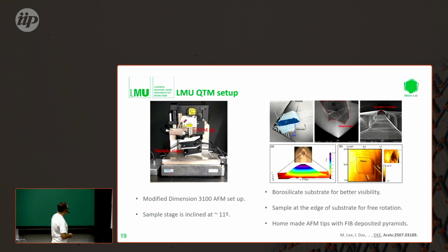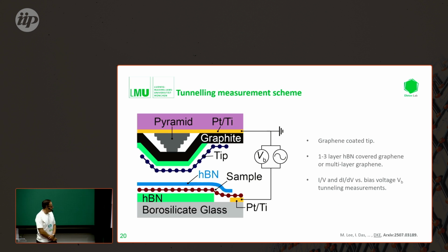Okay, so for the twisting microscope, we followed Shahal's lead, so we first built a room temperature setup of it, which is basically just an altered AFM system. We make these special tips, as you can see, where we grow these pyramids and coat them with graphene. We can take AFM measurements of the tips to identify the plateau structure, and usually we form flat regions of around 200 nanometers, which are very well covered with graphene.